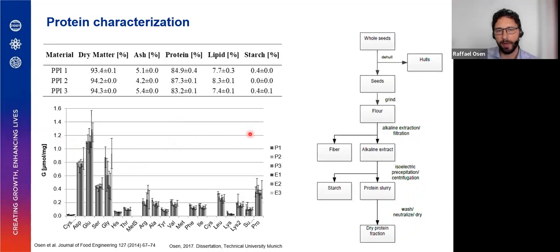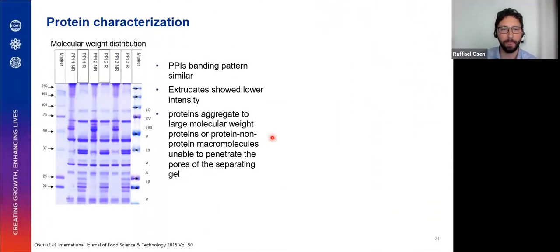We then looked into the amino acid profile, thinking maybe it's a difference in the cysteine. Cysteine can form disulfide bonds, which is important for the texturization process. Here we also didn't find any hints to explain that kind of different behavior. We looked into the molecular weight distribution, and also here we can see that the banding pattern is fairly similar between protein number 1, number 2, number 3.